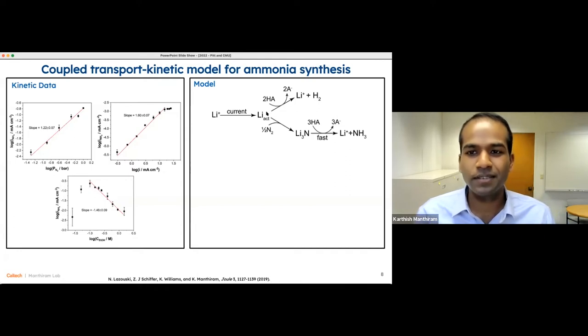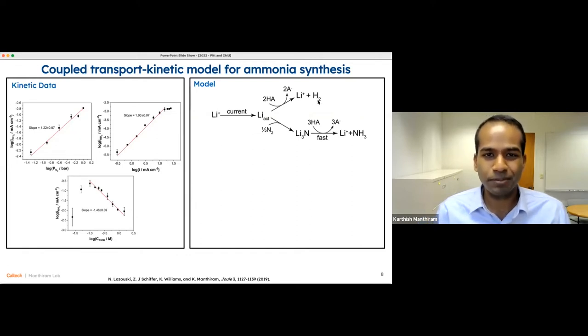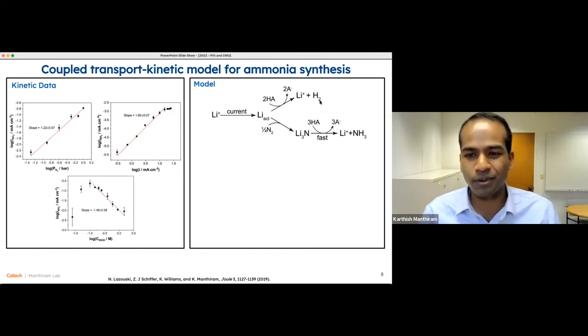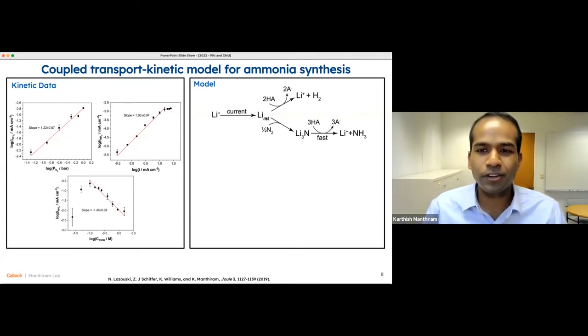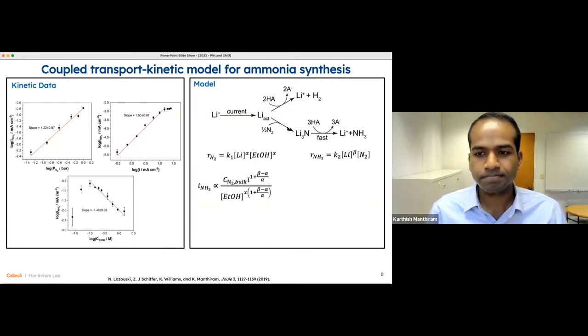But that lithium metal is not guaranteed that it'll react with dinitrogen. It could just as easily react with proton donor in solution, which in turn would generate hydrogen as a product. And this is the side reaction that we're fighting. So if lithium metal can be intercepted by dinitrogen first, we will get to our desired product. But if it doesn't, we end up with a side product. So we really need to figure out how to facilitate nitridation.